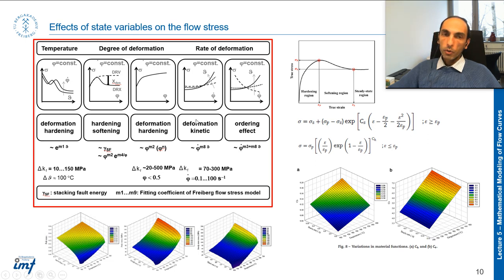And of course, maybe you know that you can combine these two, temperature and strain rate, together in a parameter which is named the Zener-Hollomon parameter. Then you can discuss the effect of both using the Zener-Hollomon parameter. And we talked about it in Fundamentals of Metal Forming before. So for the effect of strain rate, we can formulate in this way because it's a kind of exponential change here, and the constant is given as m8 here.